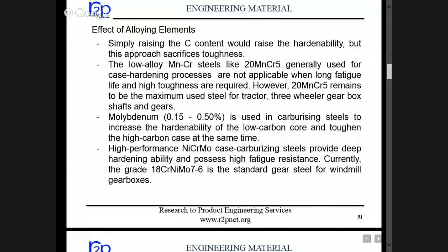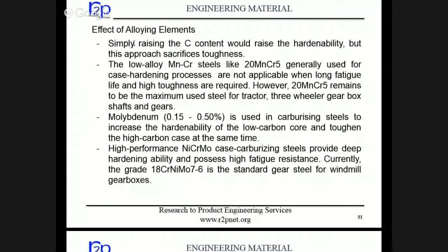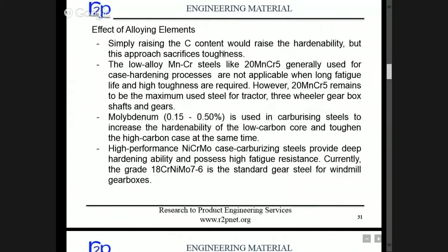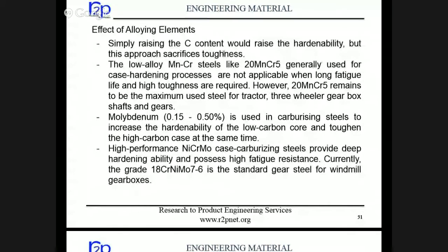Now, in brief, this is very interesting information on the effect of alloying elements, because hardness of a component depends on the carbon percentage, right? The alloying elements' role in hardness is very less. So we can achieve the desired hardness by increasing carbon also, right? But it has its consequences. Simply raising the carbon content would raise the hardenability, but this approach sacrifices toughness. The toughness of the core will also become poor, and it will feel like a brittle fracture.